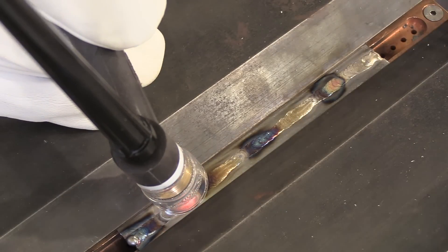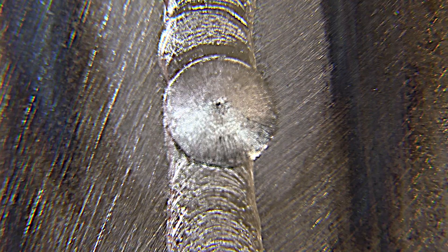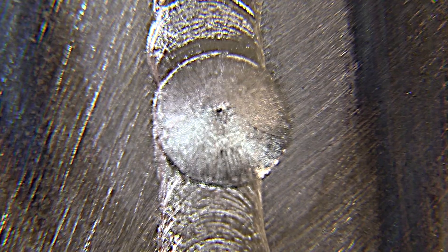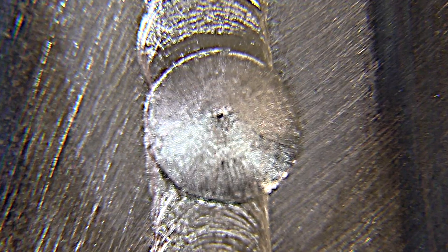Let's take a look now at what happens when you let off the amperage quickly without tapering off. See that dot in the middle there? That shows up big time on an x-ray, and on certain alloys, you'd almost certainly have a crack in there too.